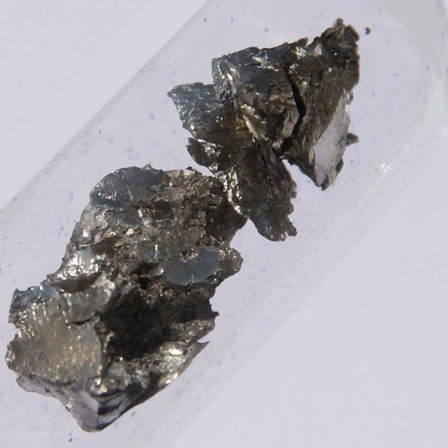Bastnäsite is usually lacking in thorium and the heavy lanthanides, and the purification of the light lanthanides from it is less involved. The ore, after being crushed and ground, is first treated with hot concentrated sulfuric acid, evolving carbon dioxide, hydrogen fluoride, and silicon tetrafluoride. The product is then dried and leached with water, leaving the early lanthanide ions, including lanthanum, in solution.